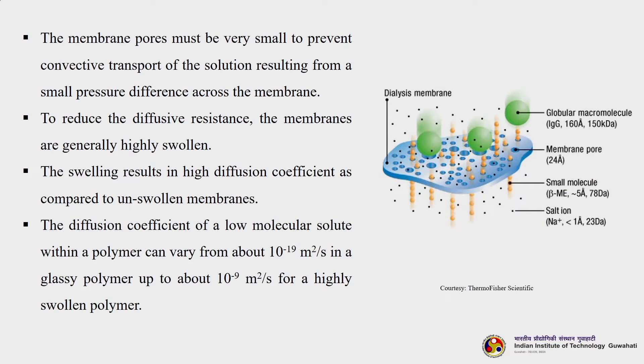The membrane pores must be very small to prevent convective transport resulting from a small pressure difference across the membrane. To reduce diffusive resistance, membranes are generally highly swollen; swelling results in high diffusion coefficients compared to unswollen membranes. The diffusion coefficient of a low molecular weight solute within a polymer can vary from about 10⁻¹⁹ m²/s in a glassy polymer up to 10⁻⁹ m²/s for a highly swollen polymer.